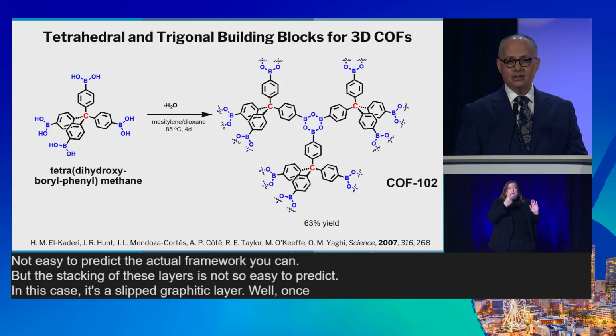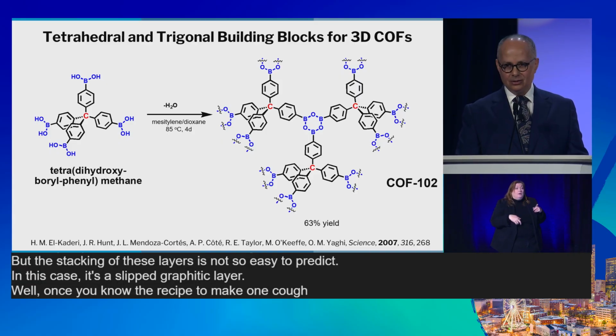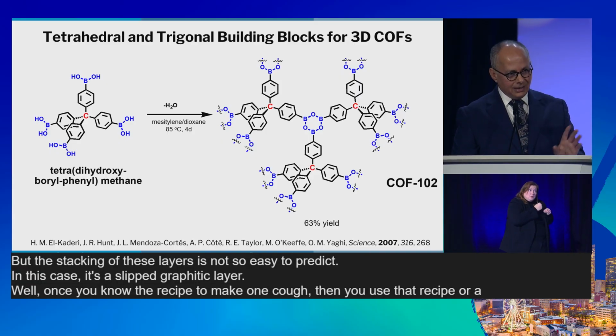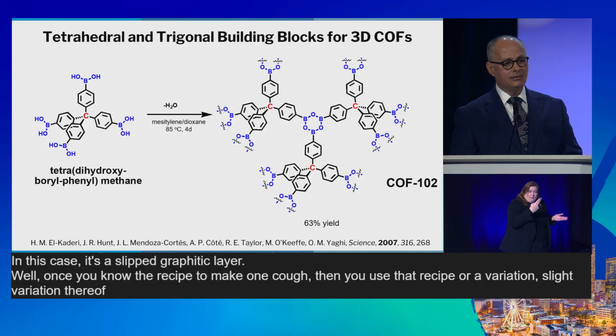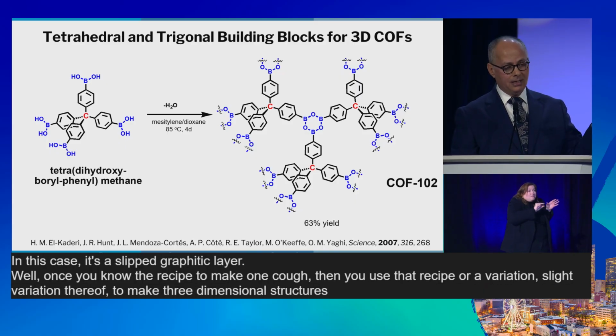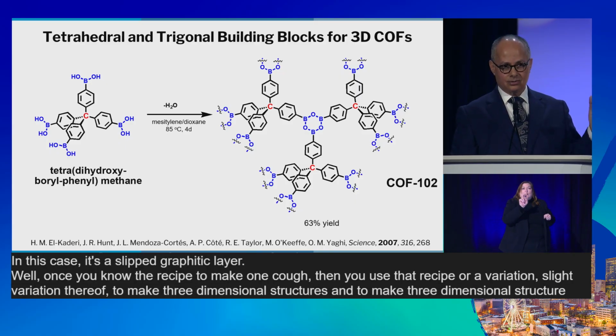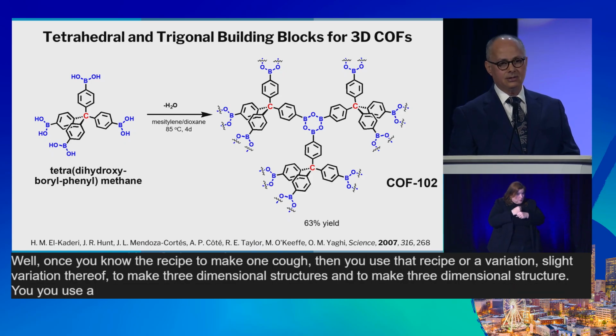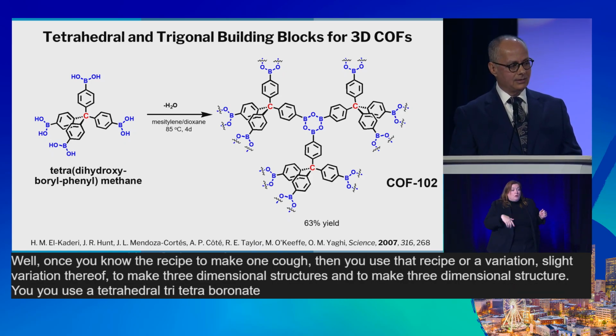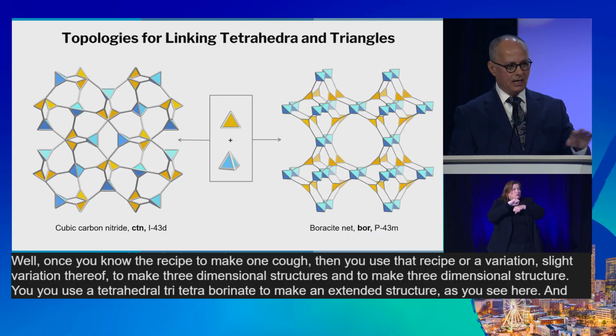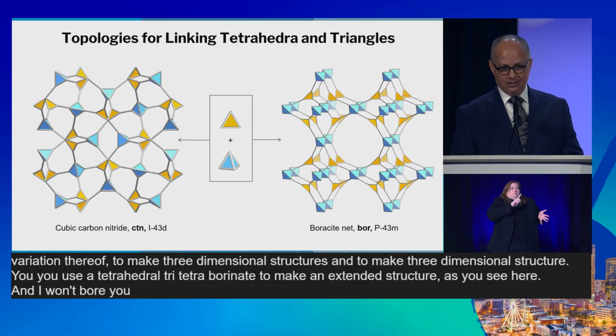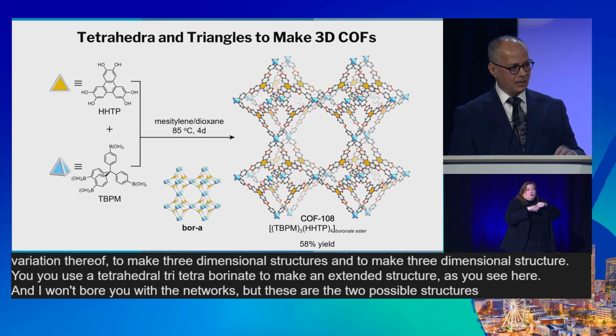Well, once you know the recipe to make one COF, then you use that recipe or a slight variation thereof to make three-dimensional structures. And to make a three-dimensional structure, you use a tetrahedral tetraboronate to make an extended structure as you see here. And I won't bore you with the networks, but these are the two possible structures. Needless to say, we made both.